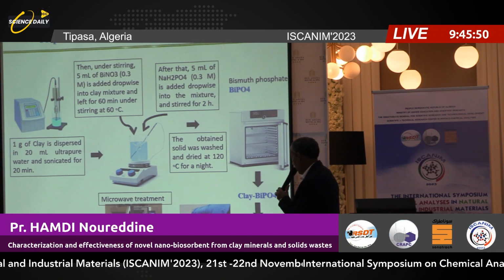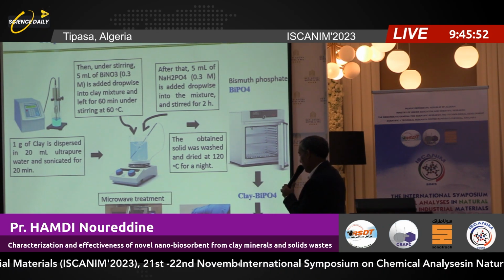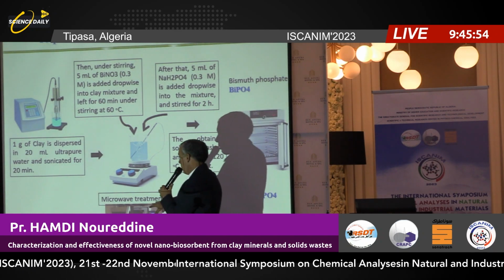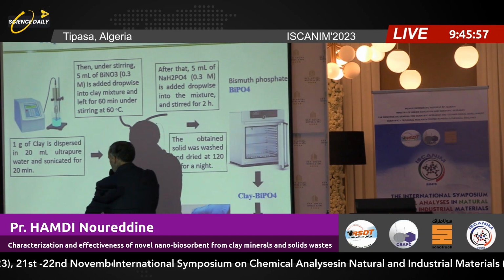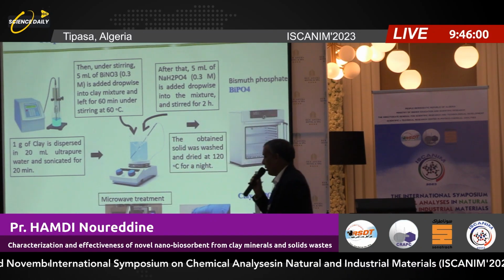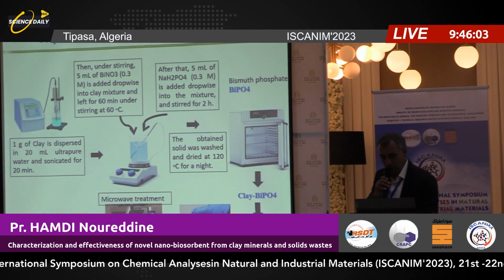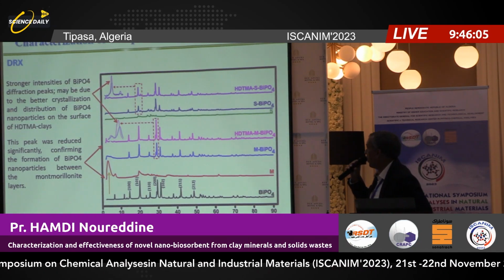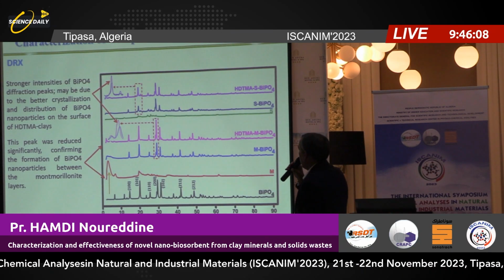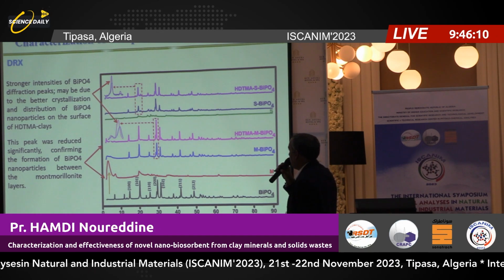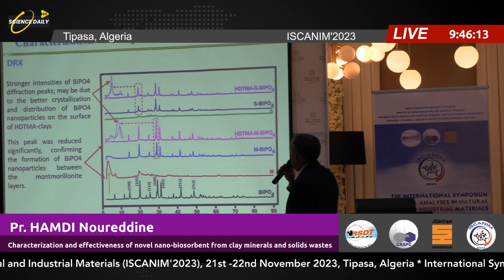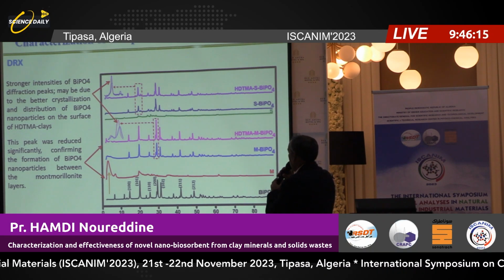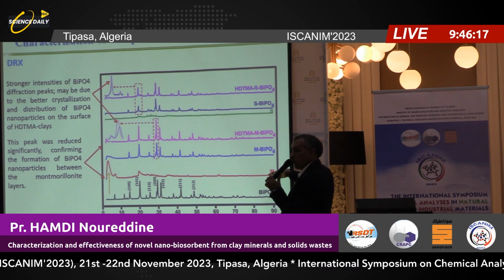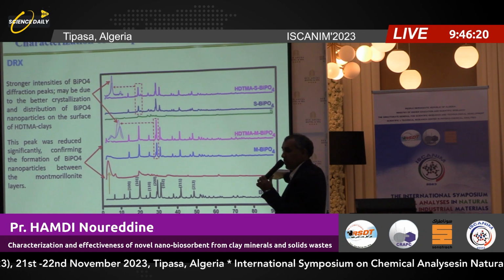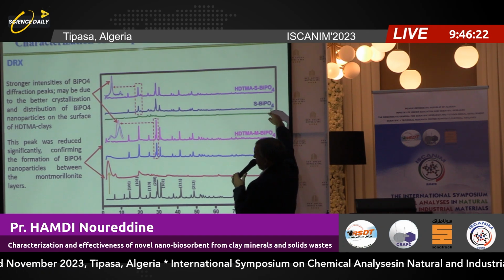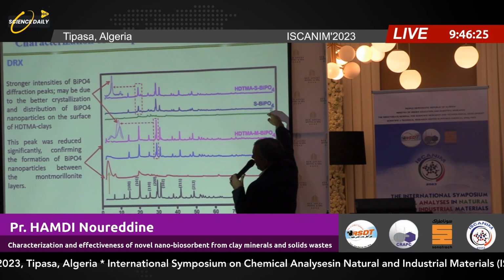When we add the HDTMA, the surfactant, and apply a microwave treatment, we obtain the composite HDTMA, clay, and bismuth phosphate. The characterization now by X-ray diffraction gives an idea about the modification of the structure of our clay and the composite. Here, clay number 1 is M, the clay from Marnia, Algeria, and the second one is the smectite from Gabes, Tunisia.